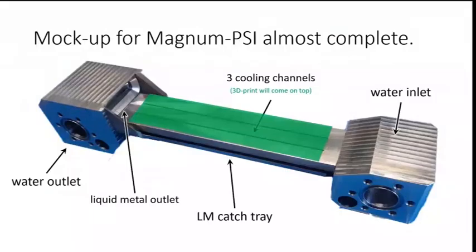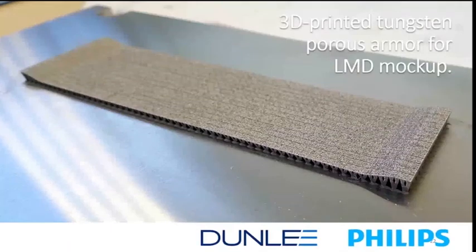I'll show you again. The channels in between these that go through this array are pointed perfectly vertical. There you have very smooth flow, and the space in between appears to just get filled up with capillary forces. That's the most important thing. Then for the flow speed, of course, it should be more than sufficient to compensate for the evaporation that you expect. But it turns out that the evaporation rate is indeed very low.